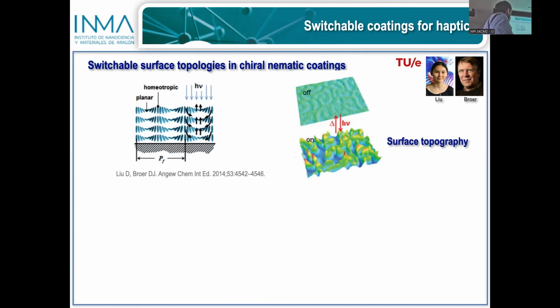In this case, what they did was to use these reactive mesogens, these low molecular weight molecules provided with acrylate groups and doped with a chiral dopant, and then they put this material on top of a substrate. The treatment of the surface is such that the helixes lie parallel to the substrate. So the chiral nematic liquid crystal helixes are organized in this way. We can see this material as composed of homeotropic regions in which the molecules are pointing upwards, or planar regions in which the molecules are parallel to the substrate.